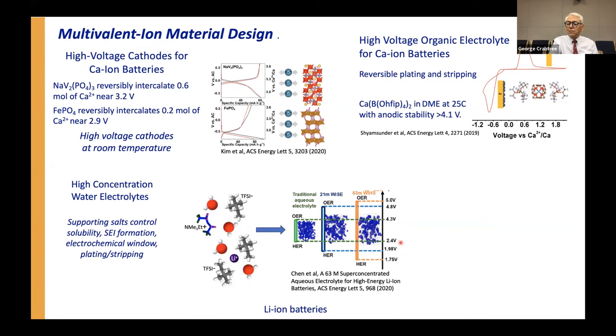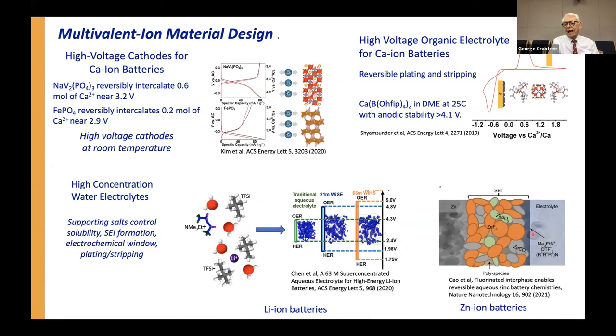If you do the same thing for zinc, so that's this with a different anion, and of course a different cation, it raises the solubility, but it also sort of forces the reaction for a protective layer. It has zinc sulfate in it, it has zinc carbonate and zinc fluoride, a couple of other things. We don't know too much more about it other than its composition. But this transmits zinc, but nothing else, no electrons, and enables very high efficiency stripping and plating across the zinc electrode. So this is very promising for a zinc ion battery.